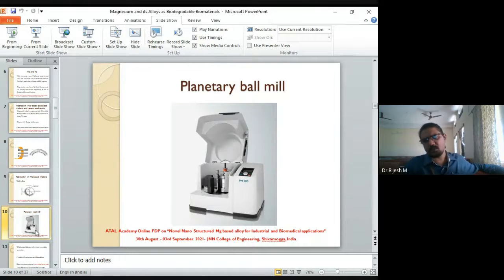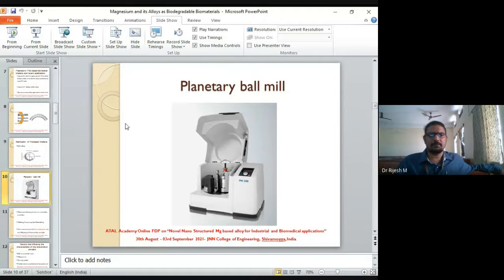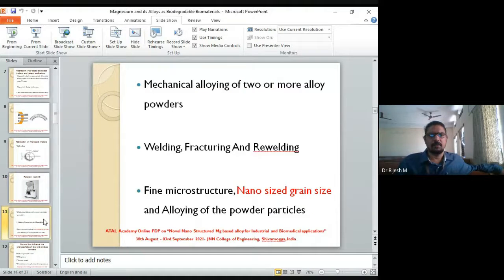The one that has been used in many of the laboratories to do this is called a planetary ball mill. We use a planetary ball mill to reduce the size to nanocrystalline size. Sometimes if you do not have an alloy and you want to make an alloy, what we do is we mix two different powders and then go on doing this ball milling for a longer time.